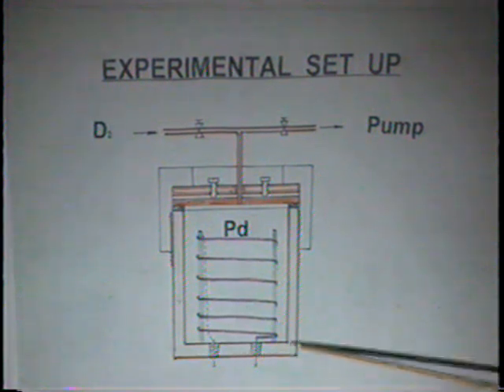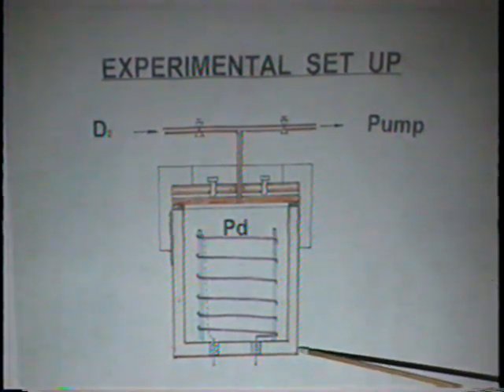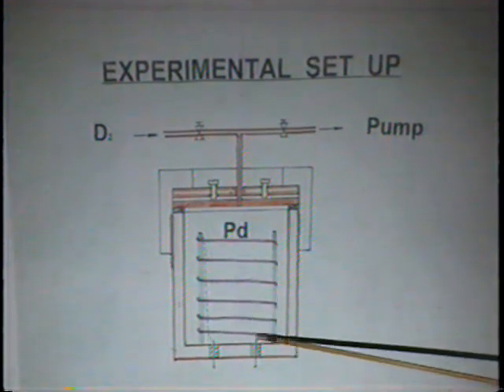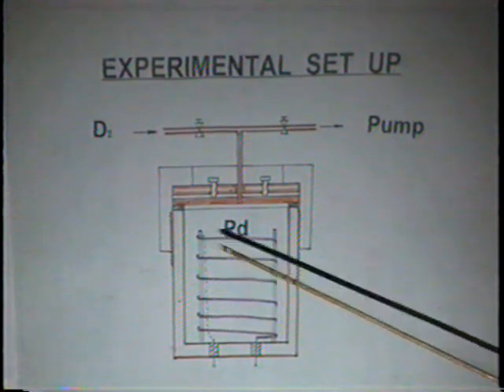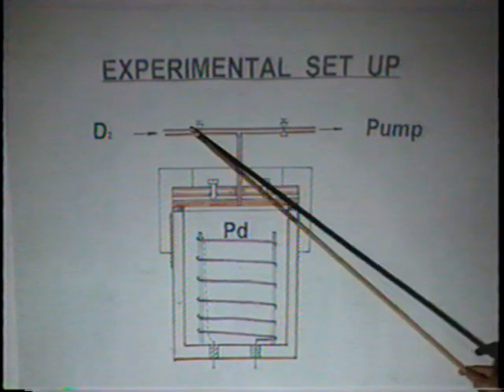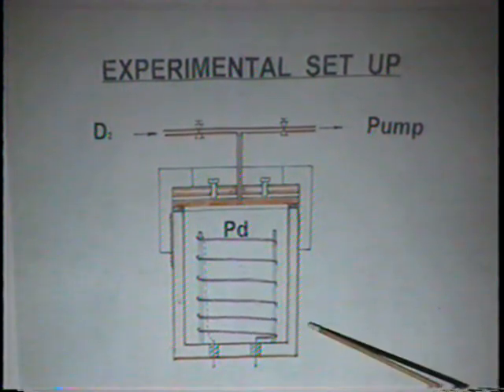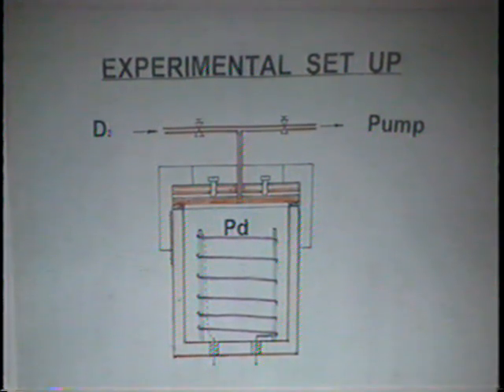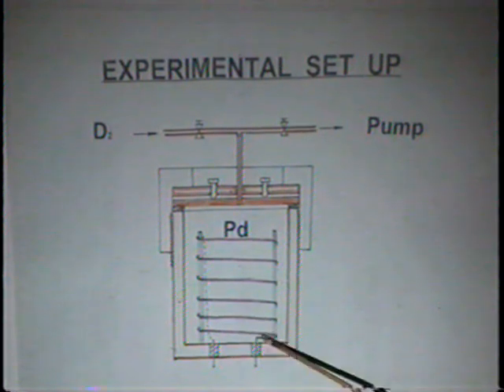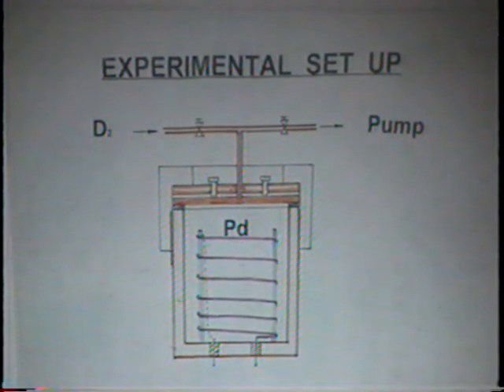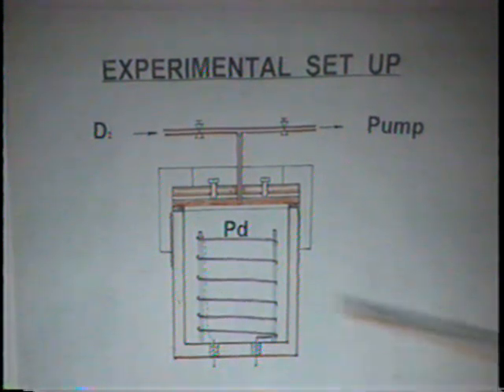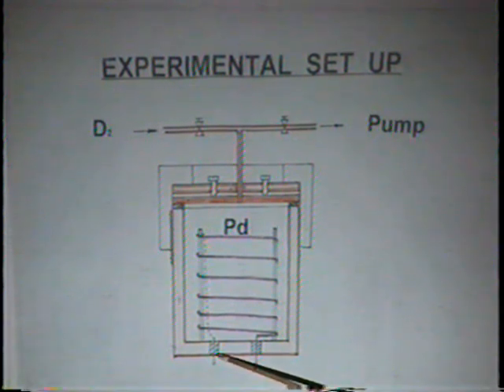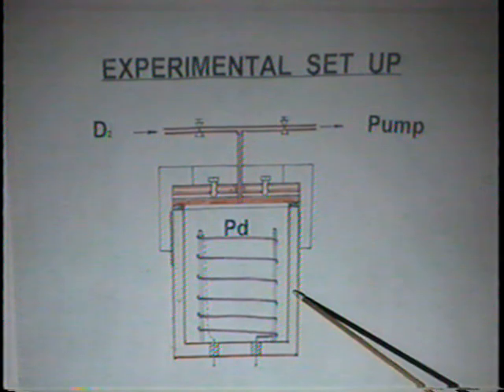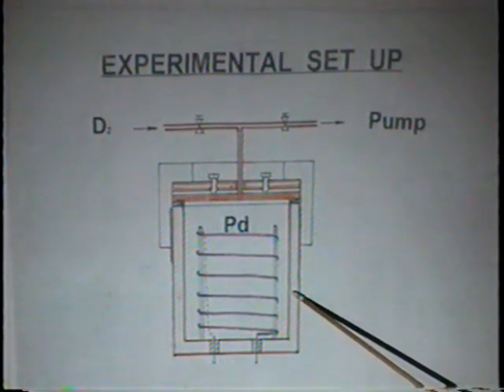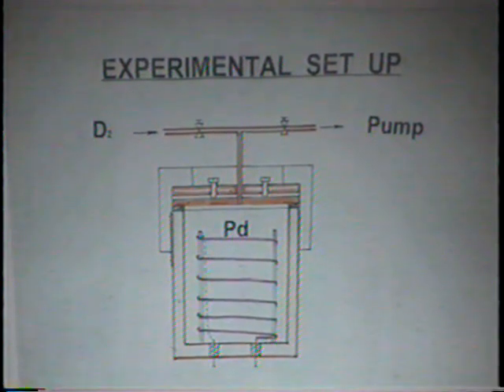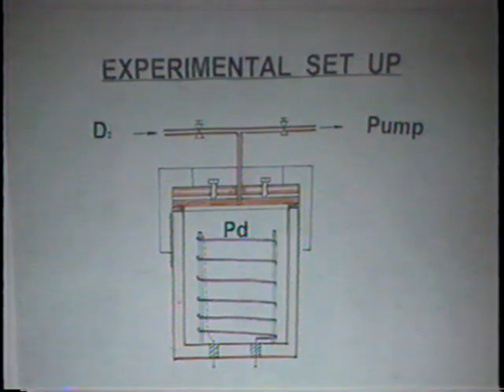This yellow part is a stainless steel container with ceramic support, and this red one is a palladium wire, and it's sealed. We can pump it and put deuterium gas in. We try to use this system to study 3 kinds of effect. First, we can heat this wire just by large current and see what the effect is. Then we can cool it by liquid nitrogen outside, to make the temperature low. And we can create a kind of discharge between the wire and the stainless steel wall. At the same time, we can monitor the resistance of this wire to get the number for the loading ratio.